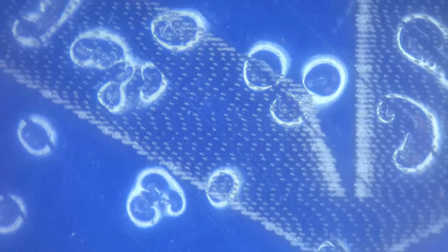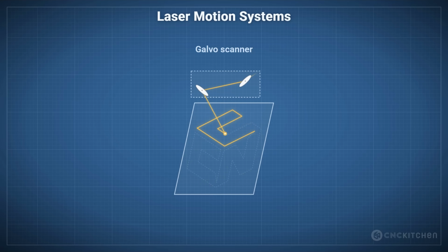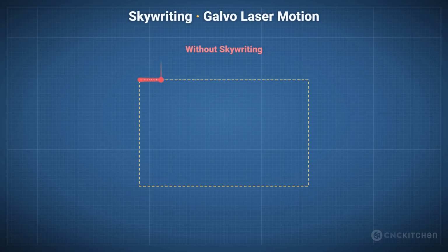One more thing I noticed under the microscope, and this is a bit of a tangent here, but I think it is very interesting. The engraving often wasn't a continuously filled area. It consisted of many tiny dots, which really show the pulsed nature of the laser. But the dots were closer together near the edges of the engraved areas and more spread out in the middle. This happens because even though the galvo mirrors are very lightweight, they still have to accelerate and decelerate. Near the ends of each hatch line, the scanning speeds are lower, so the pulses land closer together. In the middle, the laser is moving faster, so the same pulse frequency creates a larger spacing.